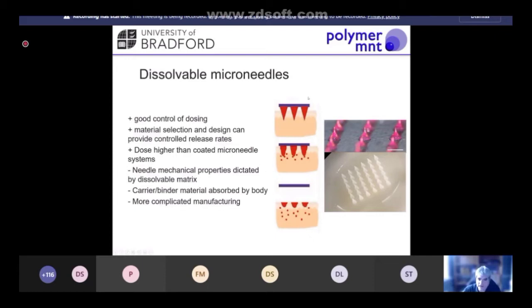The downsides of this are we can't choose a material that gives us the optimum penetration performance because we're bound to use dissolvable polymers. And typically those dissolvable polymers won't have as good mechanical properties as some of the higher quality engineering thermoplastics. So we might have a softer needle that's more likely to bend, which gives us slightly poorer penetration behavior.